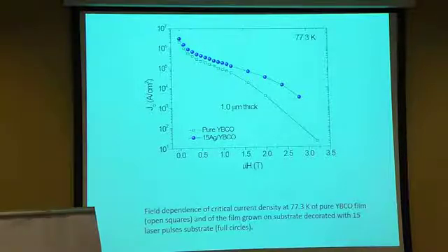So what you will see here are films which are much thicker than the films reported by other groups, which are usually with a thickness which allows them to have the optimum critical current density, and that thickness is about 400-500 nanometers.